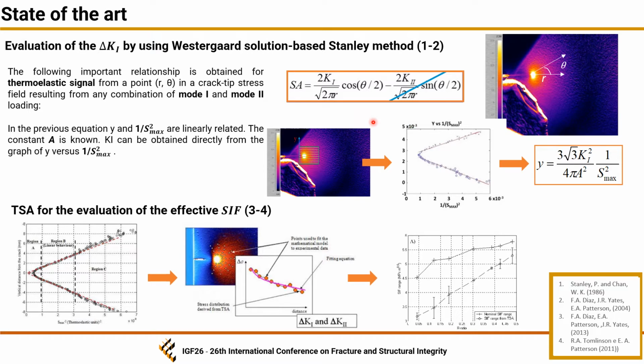is that only a series of signal profiles, in this case horizontal signal profiles scanning around the crack tip stress field and away from the plastic zone, are required to obtain the stress intensity factor measurement. The main drawback of the approach refers to the neglect of the T-stress term in the Westergaard equation, which led to an error in SIF evaluation.